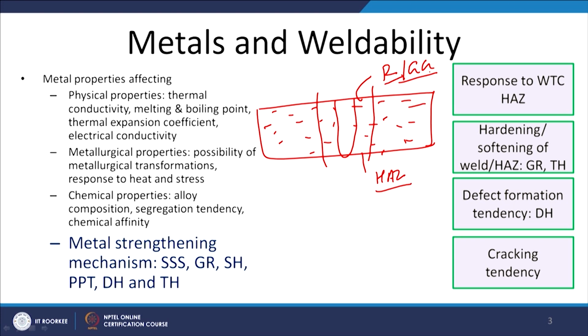So, because of recrystallization and grain growth, all the dislocations which were formed to provide the required strength to the metal will be annihilated, all these will be vanished due to the weld thermal cycle being experienced by the heat affected zone, and that is why you may find that the heat affected zone has got softened due to the loss of these dislocations which were developed in the course of strengthening of the metal. But in case of the deformation based approach, where large plastic deformation or limited plastic deformation at the joint interface is being realized, we will experience a significant improvement in the strength and the hardness of the material.